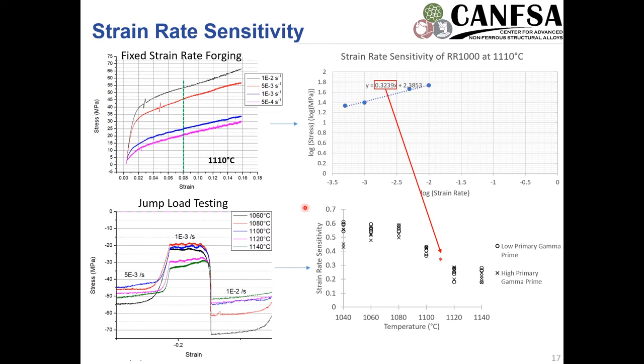But looking at the strain rate sensitivity, we approach that from multiple different aspects. One is jump load testing, where you're going through different strain rates, and then jumping and looking at the relative flow stress once you equilibrate at that point. And looking at multiple samples with a set strain and comparing those, we're able to have two different experimental procedures that achieved similar results by looking at the slope of the log of these and plotting that on this.